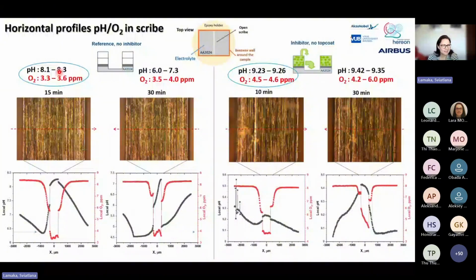So then, in this case, the active anode was introduced to the model by locally accelerated kinetics of anodic dissolution. And only in this case, we were able to have very well matching values of local current density between the ones modeled by finite element modeling and the actual SVET experimental data. While if the active anode is not taken into account, then we see very low activity predicted by the model, and so introduction of this active anode is indeed important.